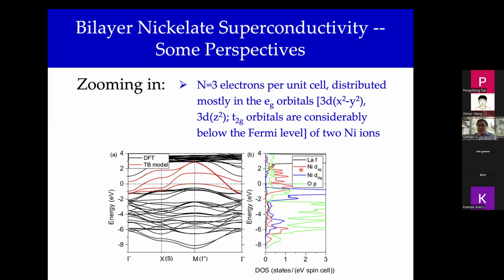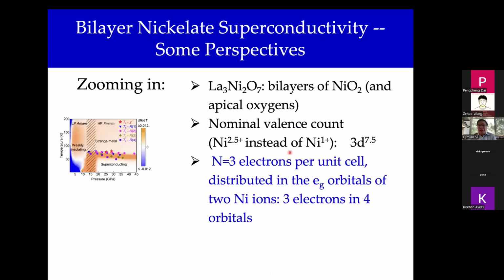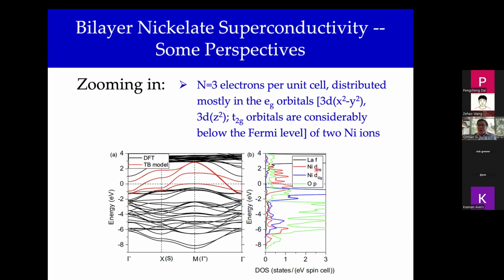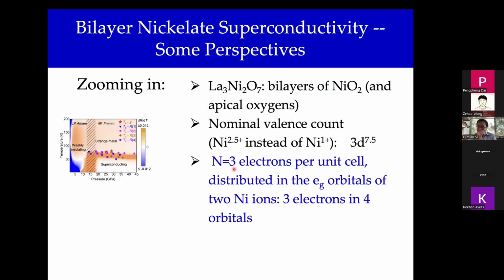So if I say that the three t2g orbitals are fully occupied, and then we have 1.5 electrons occupying the two eg orbitals, and considering that this is a bilayer system, so there are two of these nickel ions in each unit cell, we count to three electrons per unit cell distributed in the four eg orbitals. And how do we, it's a partially filled system.